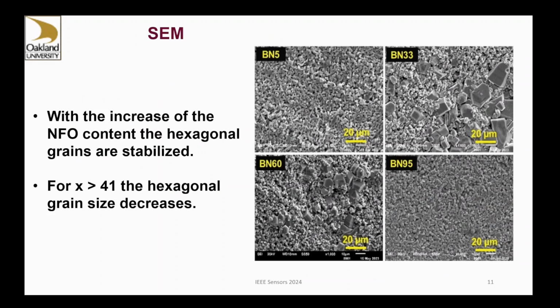So these are the scanning electron microscope images for the composites. As you see here, these are the SEM images with increasing amount of nickel ferrite. And you see here the crystallites belonging to the hexagonal ferrite, and also at higher nickel ferrite composition. But at very low nickel ferrite, there is hardly any hexaferrite crystallites, which is rather puzzling. There should be more of that.